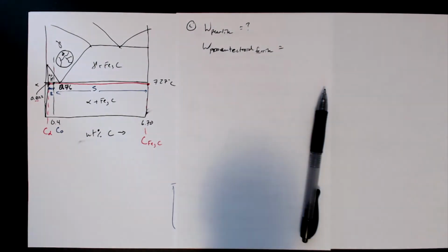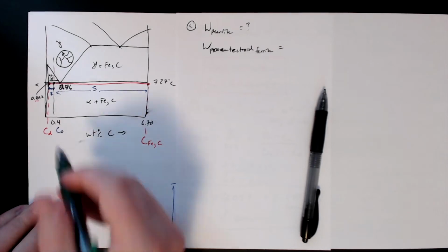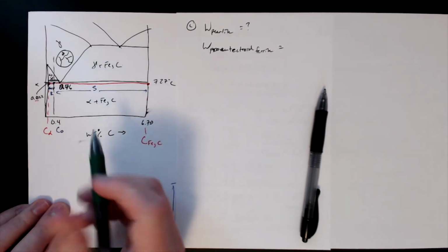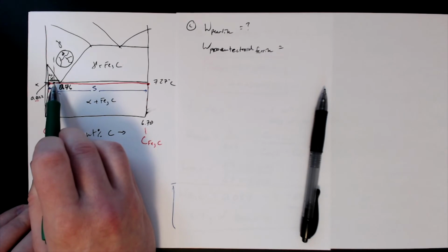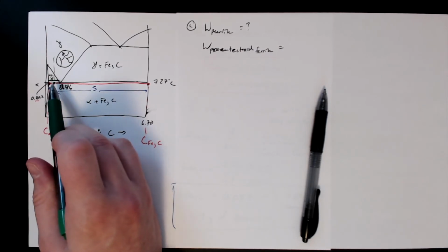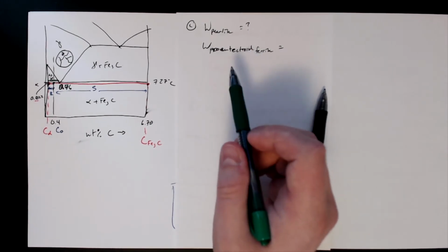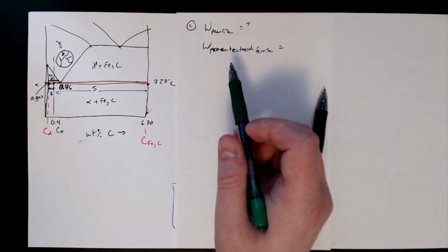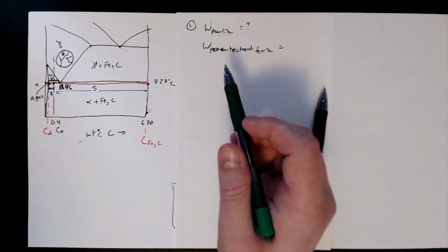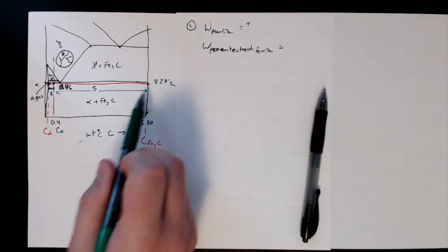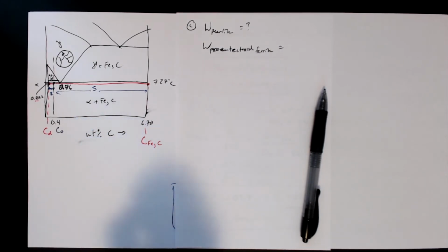And at the very end of this, just above the eutectoid, this green line that's a little hard to see, is where we have the max amount of this pro-eutectoid ferrite, right? Because it forms above the eutectoid. And so if we want to determine the amount of pro-eutectoid ferrite, we can use a lever rule just above the eutectoid of 727. So we can do that here.